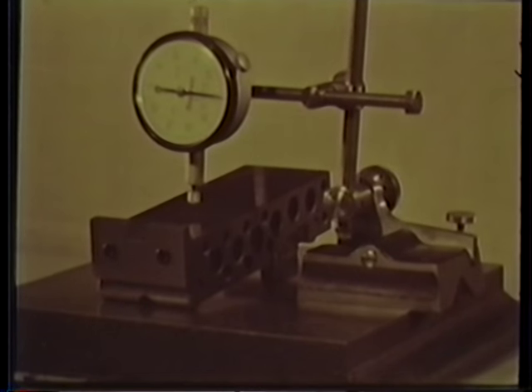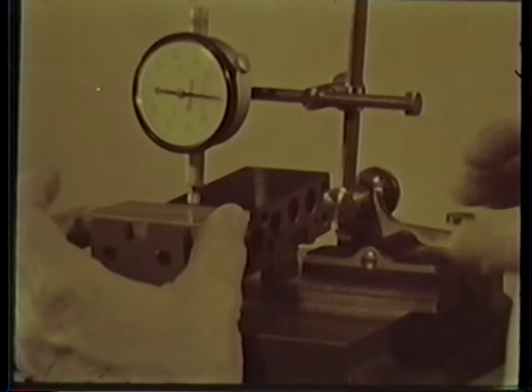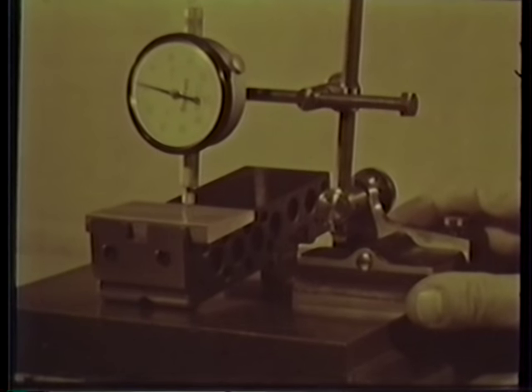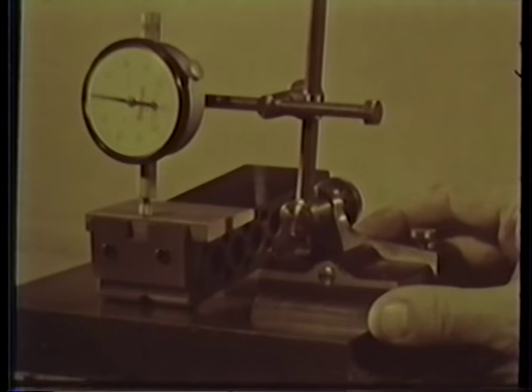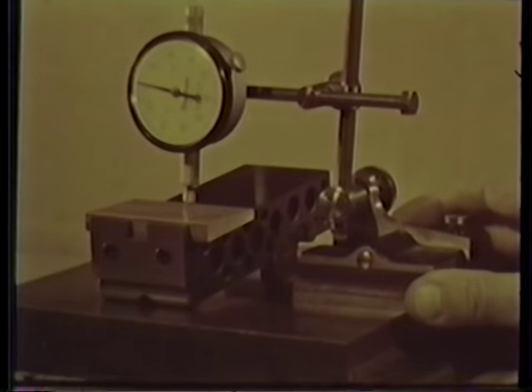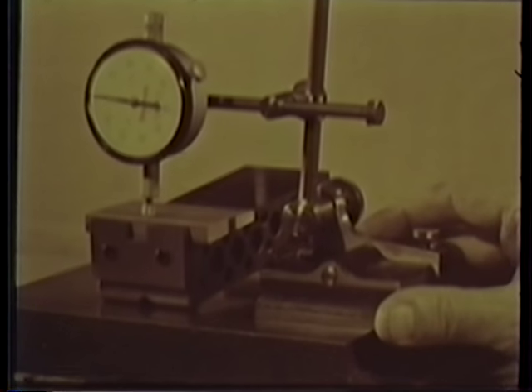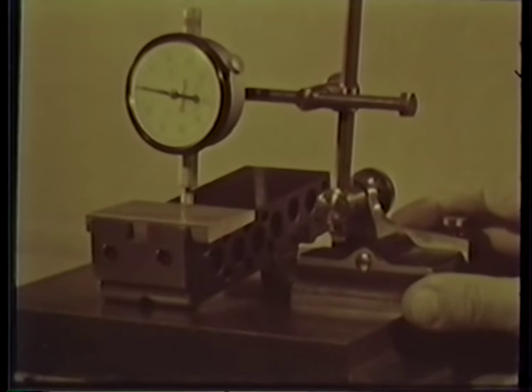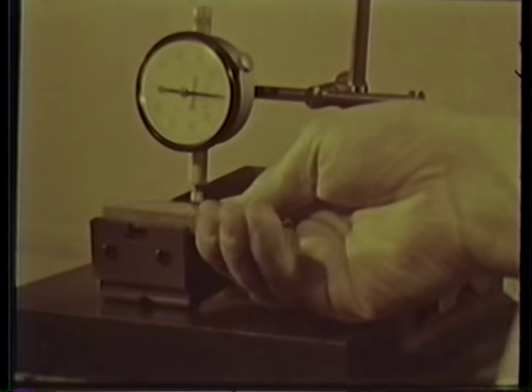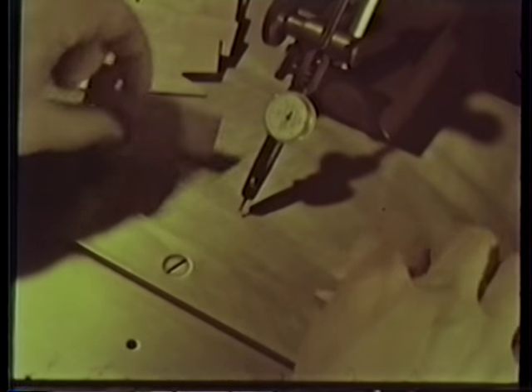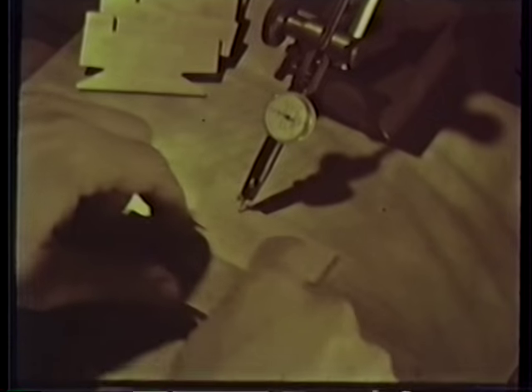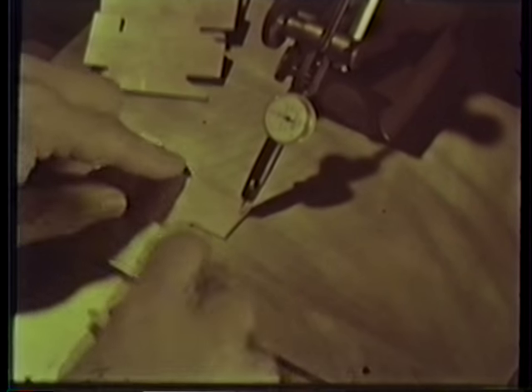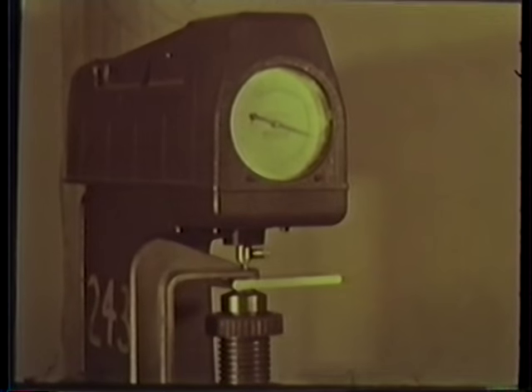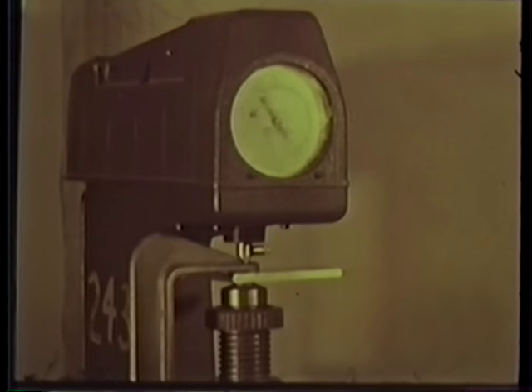While quality has been spot-checked at every operation, the copper gets a real fine tooth going over at this point. A sine bar is used to determine the angle of the wedge, the flatness and concavity, all essential to a tight commutator. The surfaces must be flat to within 2/1000ths of an inch per inch. And samples are cut off and sent to the laboratory to see if hardness and tensile strength are within tolerances.